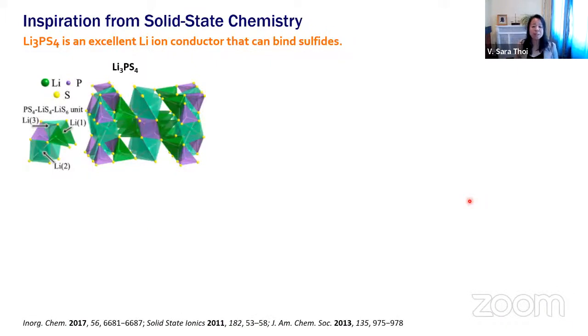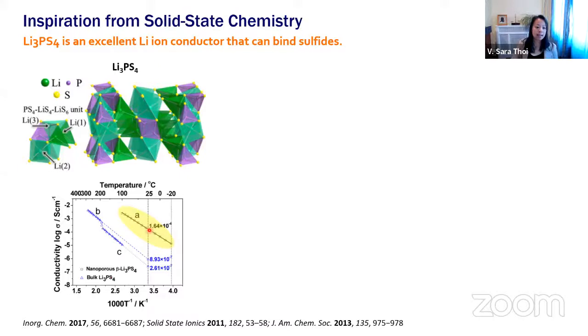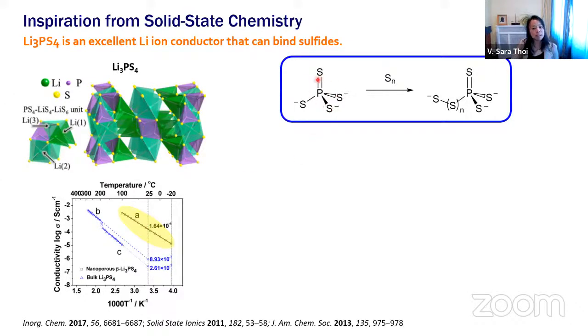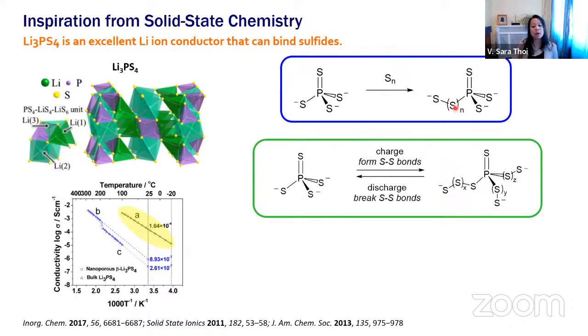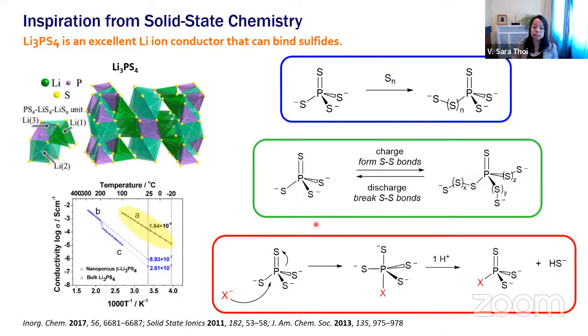So we took a lot of inspiration from the solid state chemistry world. In particular, we were really keen on these lithium thiophosphates, Li3PS4 or LPS. These materials are already used as excellent solid state electrolytes, in particular because they have really nice ion conductivity at room temperature. But as a chemist, what I was really intrigued by was the fact that these thiophosphates can bind to sulfur and form these sulfur-sulfur bonds. So kind of naively, you could maybe imagine a scheme where these thiophosphates could charge and discharge simply by forming and breaking sulfur-sulfur bonds that we have on these thiophosphates. There is a caveat to this chemistry. These thiophosphates are very sensitive to air and moisture, and undergo hydrolysis to form things like H2S. And so we need to think about a way to protect these thiophosphates in our system.